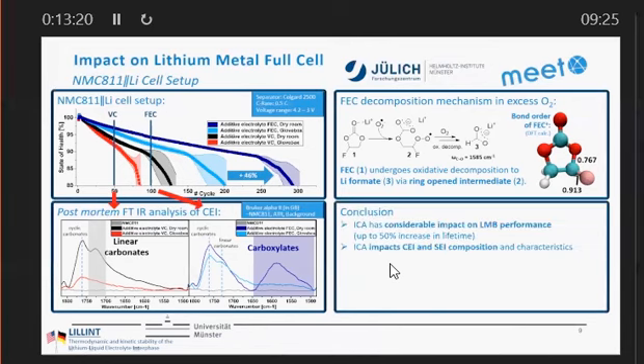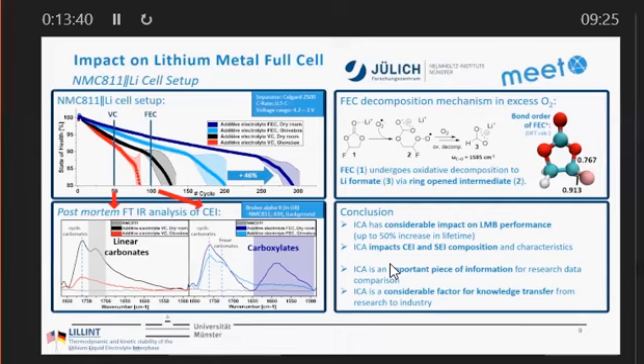And for this, we actually now also have to regard the literature that is out there. So the conclusion is that the initial cell atmosphere has a considerable impact on lithium metal battery performance, and we have up to 50% increase in lifetime. The initial cell atmosphere impacts SEI and CEI composition, and it's an important piece of information. So maybe the solution for a good lithium metal battery with liquid electrolyte is to do everything that we did in the glove box in the dry room. I'm not suggesting it, but the results are suggesting that there is some impact here.